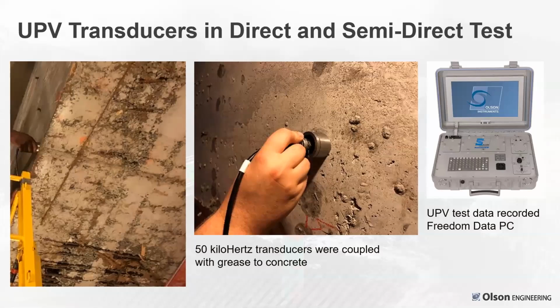So the ultrasonic pulse velocity transducers are shown here. They're grease coupled. You can see some of the grease spots right here. You can use a lithium grease or even Vaseline, something that's relatively non-staining. Don't use black axle grease. It is very staining. But here you're pushing it on with firm force, coupling on a smoother surface. If it gets too rough, that's a problem.